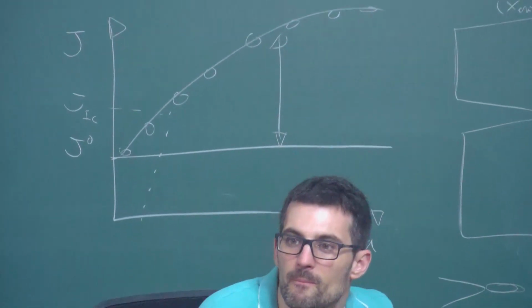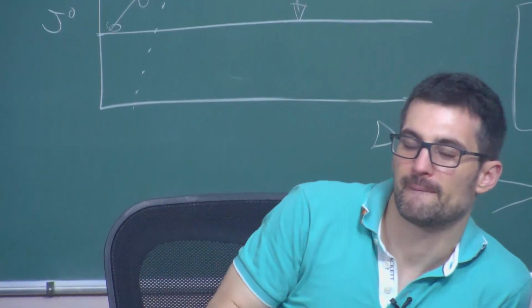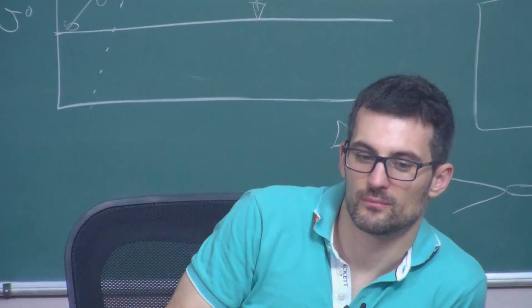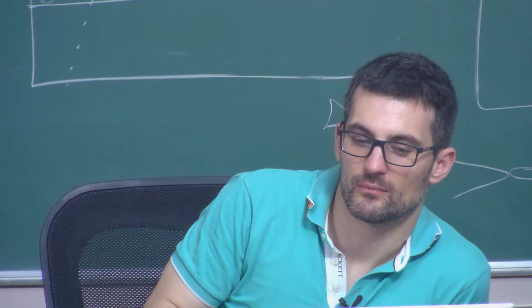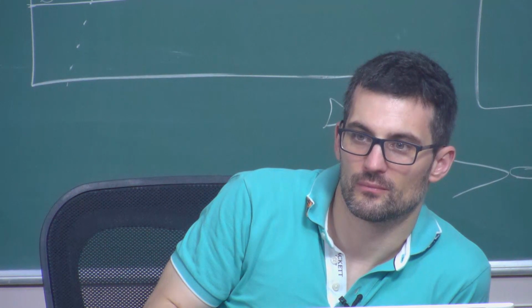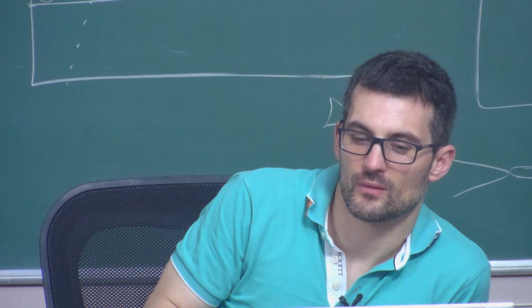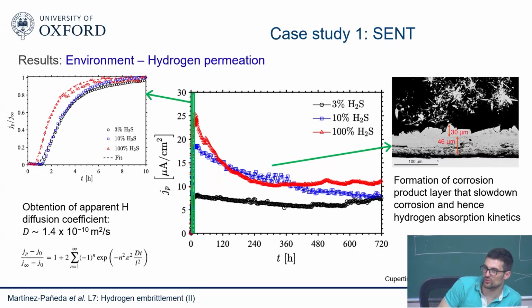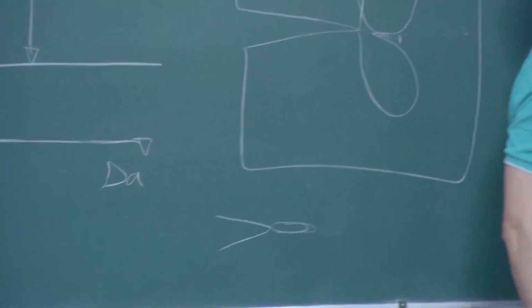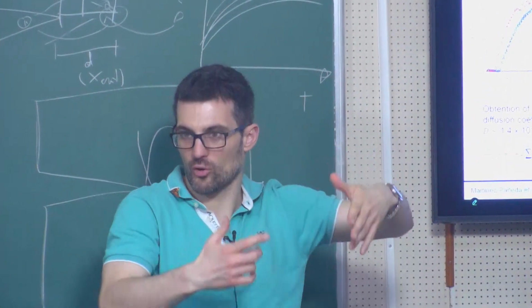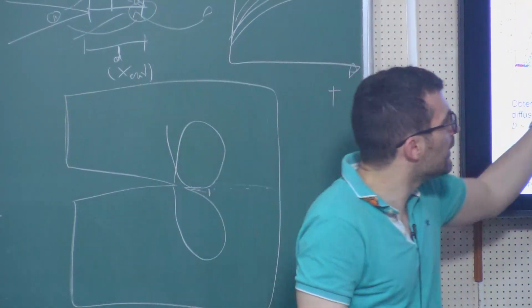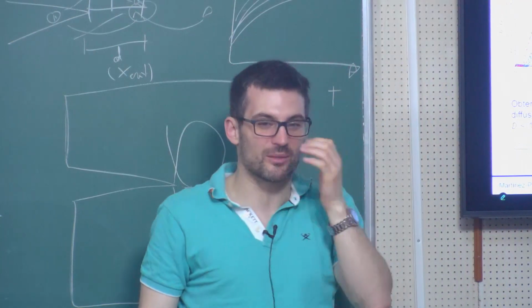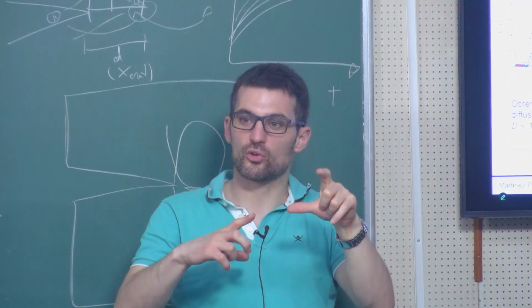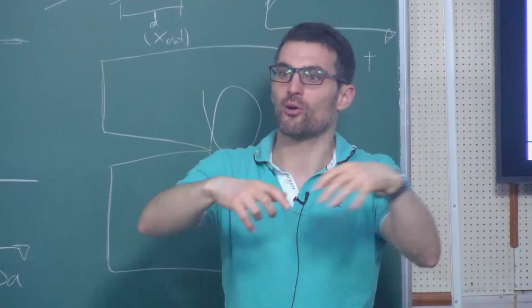But how is it possible that for 100% H2S and 10% H2S, at a certain point at say 60 hours, the 10% H2S concentration is leading the 100% one? Why did those lines cross? So I think initially you see the expected behavior. The more H2S, the more you slow the recombination reaction, so the more hydrogen you bring in. Then what happens after that is a bit complicated, because the percentage of H2S will also govern how much of those corrosion products you form and so on.